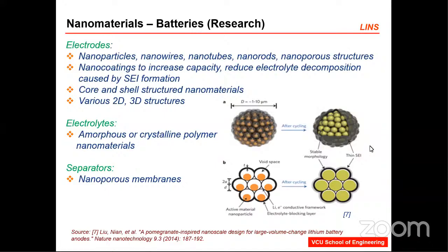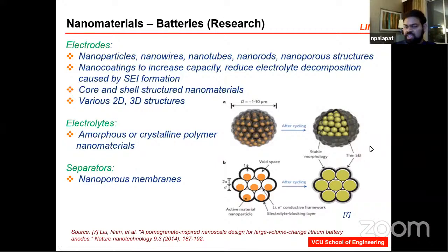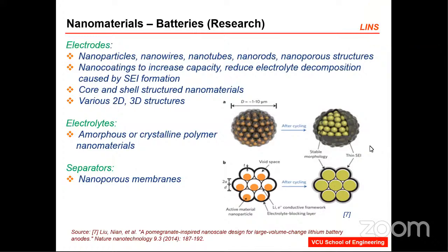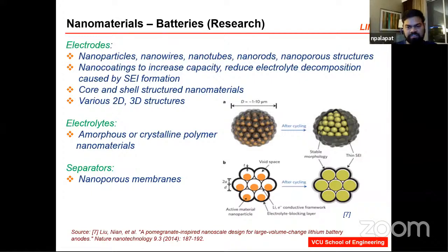that I really liked. It's a pomegranate-shaped anode battery that someone came up with. It is very interesting how one person is able to design these batteries. He found that in a battery during charging and discharging, we have something called a SEI, a solid electrolyte interface formation between anode and the electrolyte. This formation actually causes a lot of degradation of the energy density in a battery during your cycling. So using this pomegranate design, this researcher was able to form a stable interface and thereby increase the life of the battery.